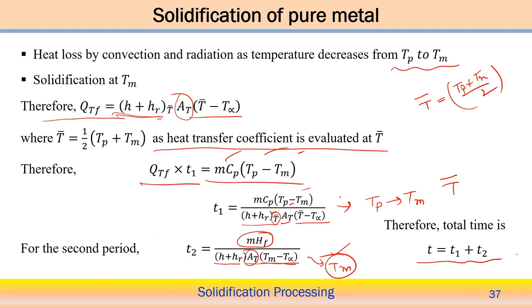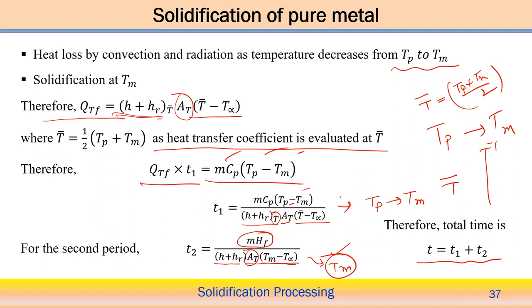Of course we can calculate directly from the peak temperature to the melting point temperature. But if we do this calculation directly, the question is at which temperature we should consider the values of the heat transfer coefficient. So if we make many divisions of the time span between Tp and Tm, and for each point calculate the average temperature, and at each average temperature calculate the heat transfer coefficient, then the results might be more accurate. In each case we can find t1, t2, t3, t4, t5 like that.